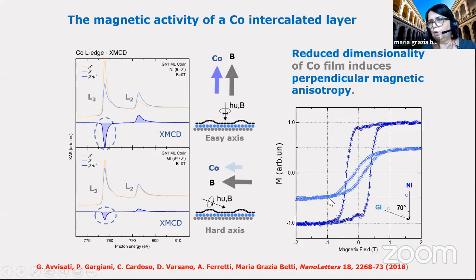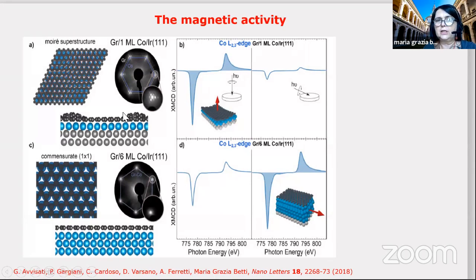If you now look at the hysteresis, we will see that the hysteresis we have with normal incidence has a saturation that is higher with respect to the saturation we have with grazing incidence. What does it mean? In the magnetic state of the cobalt, we have a perpendicular magnetic anisotropy. This is interesting because it's different from the bulk, where it's not perpendicular, but parallel to this plane. So in this configuration, we have an easy magnetization axis, and this easy magnetization axis is perpendicular to the plane.